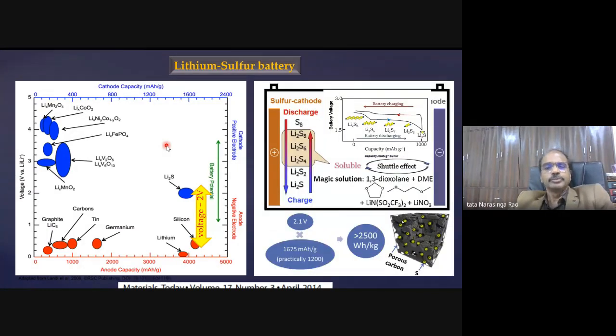But there is a challenge in lithium sulfur battery. Why? Lithium sulfur batteries have been known for decades, but not implemented because during lithiation, discharge, the sulfur takes lithium and forms polysulfides, Li2S8, Li2S, all of which are soluble. So from the sulfur, these dissolve in the electrolyte and go to the other electrode, and you lose a lot of sulfur during the shuttling, and then the battery slowly dies. So your dream of high energy density lasts only a few cycles, maybe 20, 30, 100 cycles, whereas actual batteries require 1,000 to 1,500, even 2,000, if you want to really use them for electric cars.